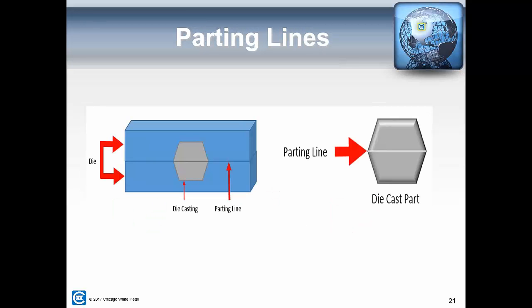So here's just an example of what a parting line would end up looking like on a part itself. This one's pretty simplified, with just being halfway across. The parting line will be present on all die-cast parts. However, if you're using good part geometry, you're able to either eliminate it completely by moving the parting line to an edge of the casting, so it will not actually appear on it. Or if it is going to be directly in the middle, there are some post-processing that can be done to eliminate the appearance of that parting line, like sanding, vibing, that kind of situation. So there are ways around having that being on the casting.